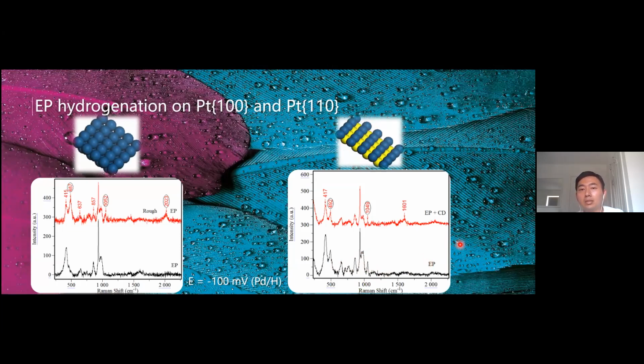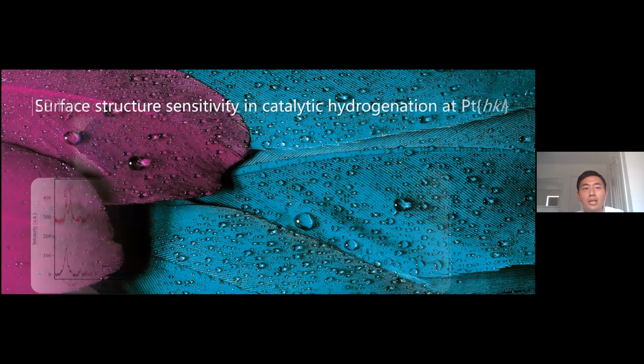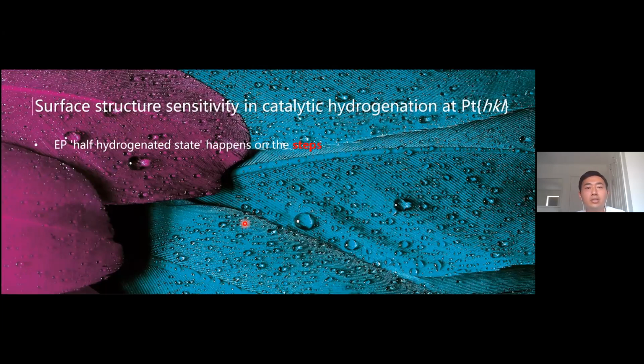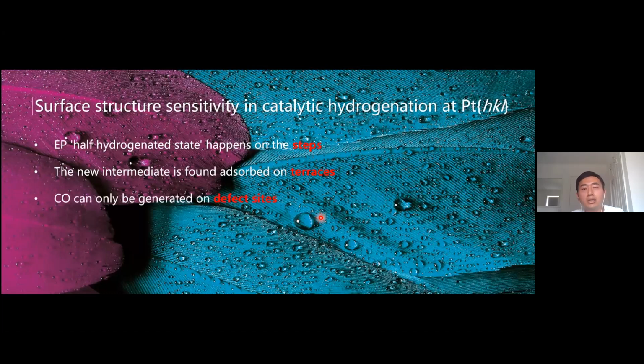To conclude, the half hydrogenated state happens on the steps, and the new intermediate was found adsorbed on terraces, and CO can only be generated on defect sites. So we know what kind of surface we need to avoid CO formation, and the CO production can be reduced by adding the modifier.